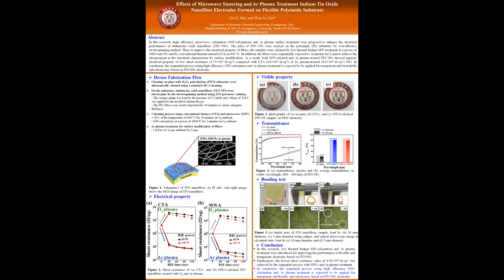In the electrical property part, figure 2A shows sheet resistance of conventional furnace, and B shows microwave-calcined ITO nanofibers treated with oxygen and argon plasma. When we applied oxygen plasma, the sheet resistance increases. However, when we applied argon plasma, the sheet resistance decreases. For comparison of conventional furnace and microwave calcination, we confirmed that the sheet resistance after microwave calcination is lower than after conventional furnace.